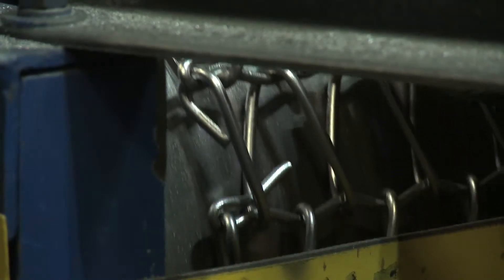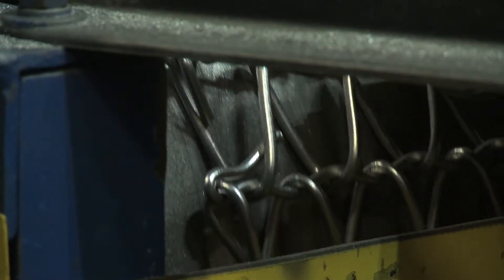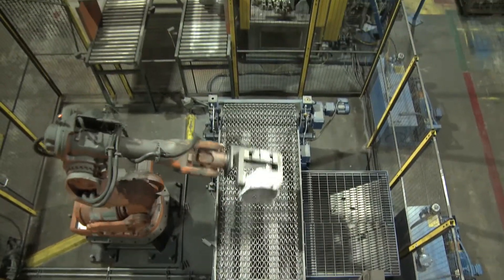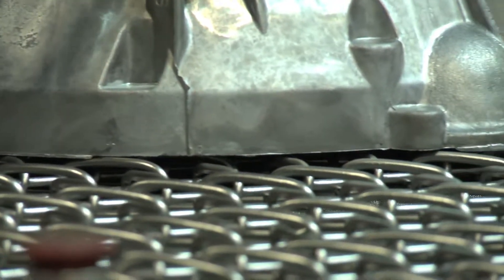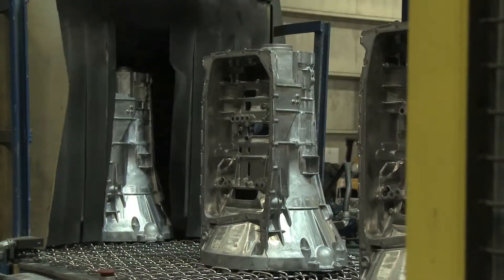During the process we run everything at a speed of eight feet per minute. All of our infeed conveyors that feed into the Wheelabrator machines are run at eight feet a minute — that's what we've determined is best for our application and process. We can run parts back to back and on some of our machines we are unloading parts every 12 to 14 seconds. With the open mesh it allows the shot blasting operation to reach inside the casting, all sides of the casting actually — there's nothing that restricts the shot from getting through.